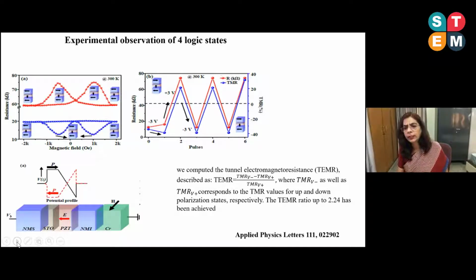From this, the tunnel electromagnetoresistance was calculated via this formula, and this ratio was found to be 2.24. This ratio is still less, and we are trying to improve it further. But the good point is that we have been able to see the fourth state in this FSMA-based heterostructure.